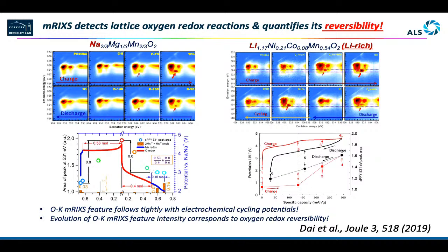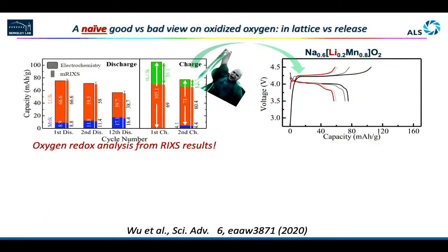And why? Because previously, we have the oxygen release. So part of the oxidization of the oxygen could come as an oxygen gas or radical oxygen release from the material, but part of them are contained in the material going through this charge and discharge process, which is seemingly what we prefer to have.